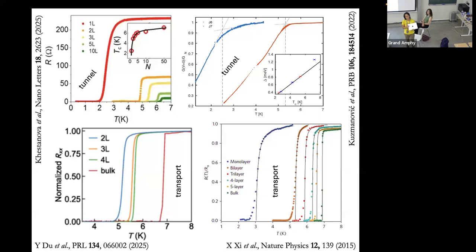So what you're actually saying is that once you go to the interesting limit, a lot of the variability between the samples is the pinning of the charge density wave, because the sensitivity of the sample to the disorder is so much. I think that in general is a fact. If you have a pin, the charge density wave is pinned there, and I think that increases the charge density wave. I don't know if it's a heavy contamination. Luckily, my feeling, that's my opinion, is that the superconductivity is less affected. Okay. So there are probably variations, but it's less affected. It doesn't really matter if you have a contaminated device, as long as the bulk drives the charge density wave; it's the worst thing that you can do.